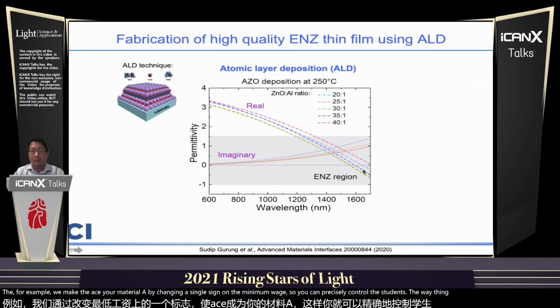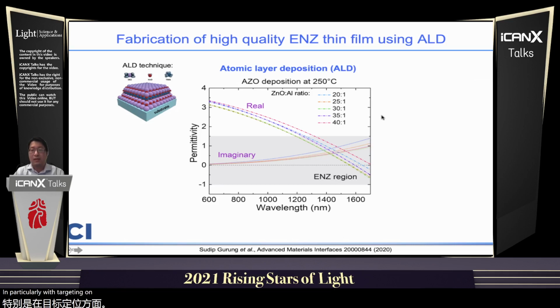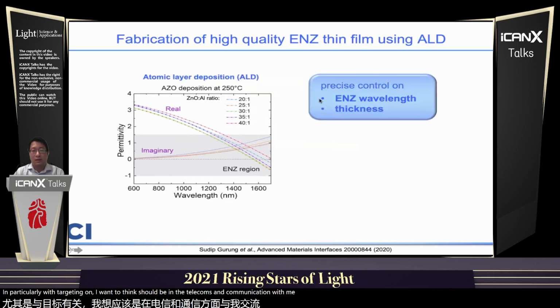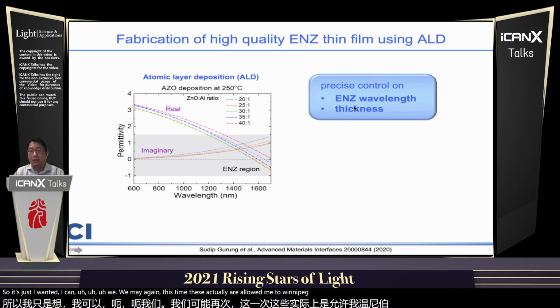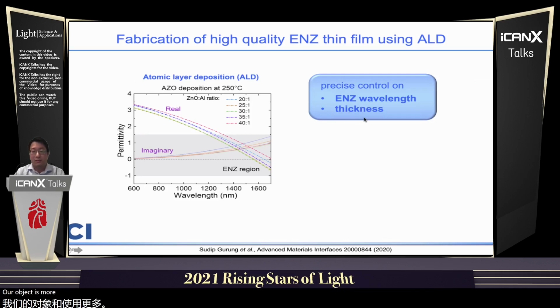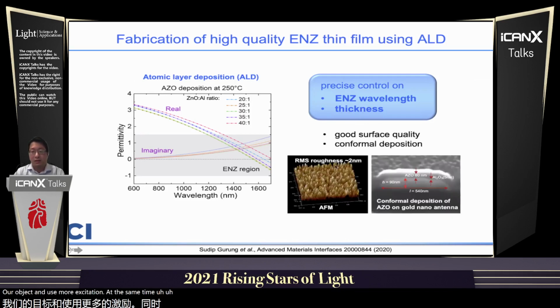And particularly we're targeting around 1550 nanometer telecommunication wavelength. Just want to remind again, this technique actually allows you to really precisely control the ENZ wavelength and thickness, which is quite important for this ENZ optics and ENZ mode excitation. At the same time, we also can get quite good surface quality and also coating of the sidewall of the metal surface because it's a conformal deposition here. So that's why we have been using this technique quite a lot to make this kind of ENZ material.